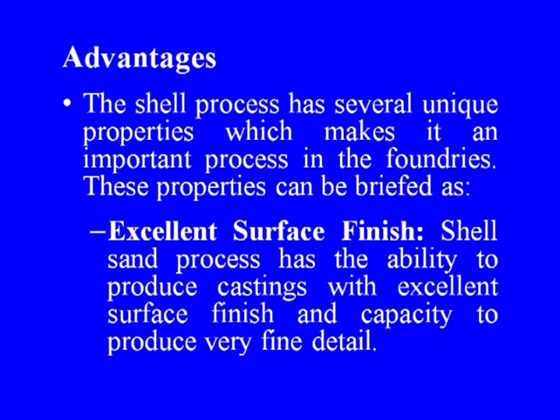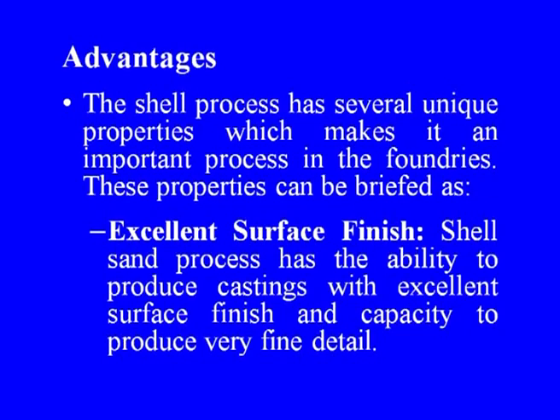The shell molding process has several unique properties which make it an important process in foundries. These include excellent surface finish — the shell sand process has the ability to produce castings with excellent surface finish and the capacity to produce very fine details. Another advantage is dimensional accuracy: the process can produce castings to tight dimensional tolerances, reducing machining allowance and thereby helping in the reduction of fettling and finishing costs.